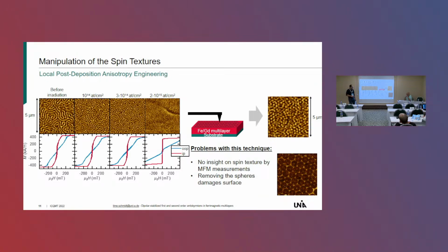And so you can see where the nanospheres were, and there is approximately 3 nanometers of film that they just rip off when they get removed, because they glue a little bit to the sample. For membranes, this is not suitable because you would damage your membrane and you wouldn't see anything.